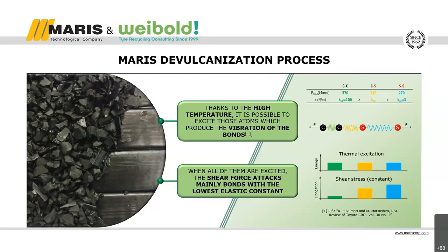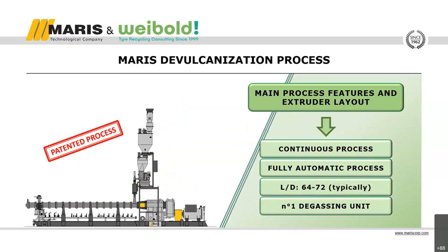Summarizing, the synergic activities between the thermomechanical energy provided from the extruder, the chemical physical characteristics of the bonds, and the right screw profile can selectively break down the cross-links between the chains, producing a devulcanized material. It's important to underline that with the same principle, we can devulcanize also peroxide bonds. Having understood the theory behind the thermomechanical devulcanization, now we can move on to other issues.